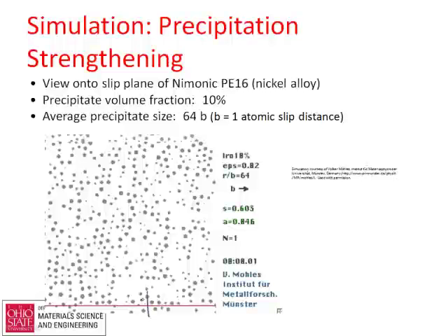You can imagine a dislocation as a force that comes up like this. As this moves along, you see that the dislocation kind of gets stuck on these bigger particles. It might miss some of the smaller ones, and it tries to move along, and it gets pinned by each of these little interactions as it moves forward.